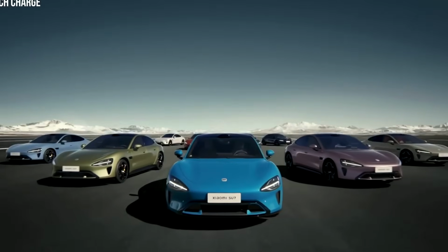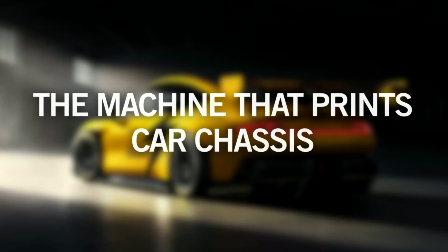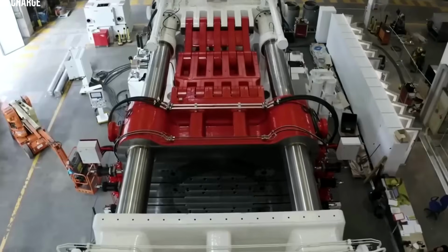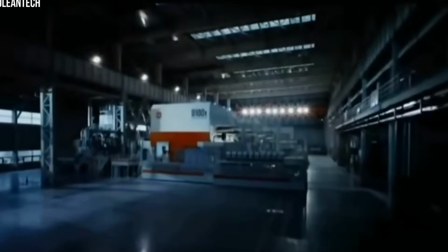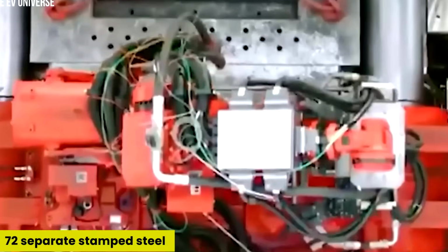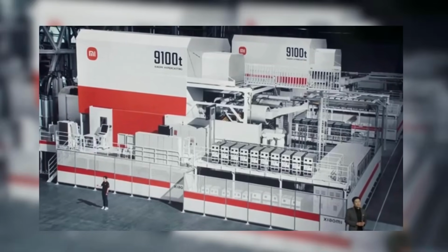To prevent the kinetic impact of the injected molten metal from physically blowing the two halves of the mold apart, the system engages its primary hydraulic locks, 9,100 tons of clamping force. Under this massive pressure, metal heated to 700 degrees Celsius fills the cavity, forming the entire rear chassis structure.